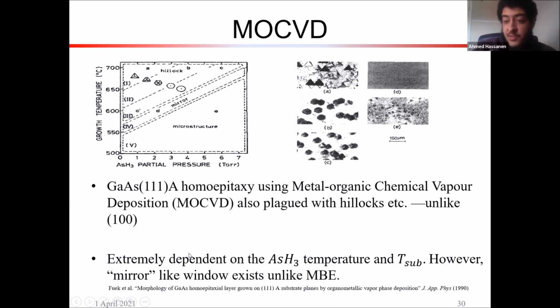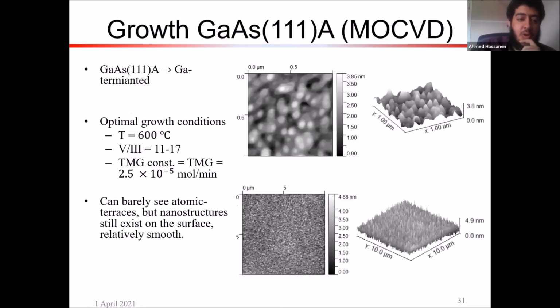Let's, without any surfactants or anything, just try some homoepitaxy on MOCVD and see what we get. Maybe we can fall into this mirror region. What happened was, first we tried gallium arsenide 111A, again the gallium-terminated version of 111, and we used temperatures from conditions similar to those in the literature.